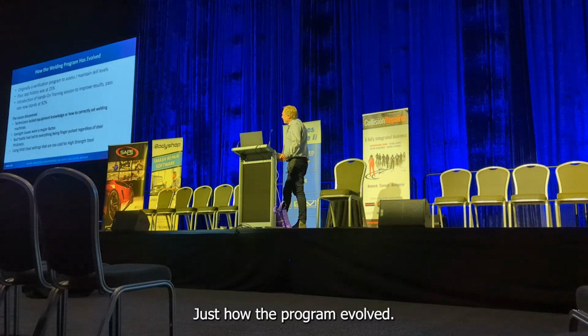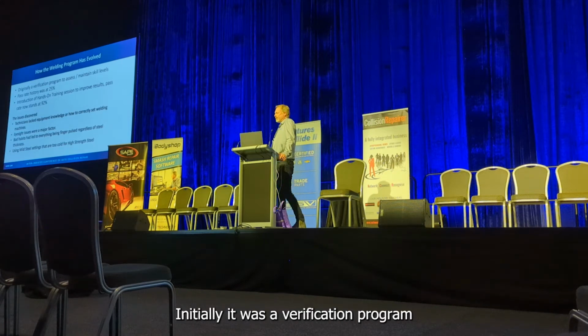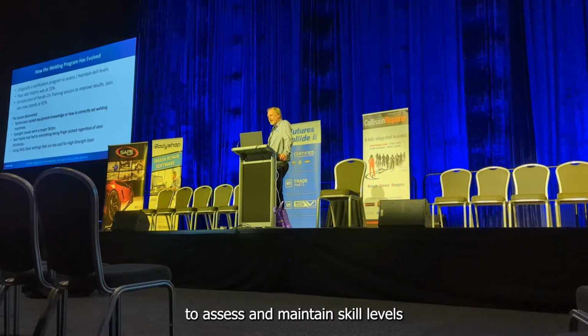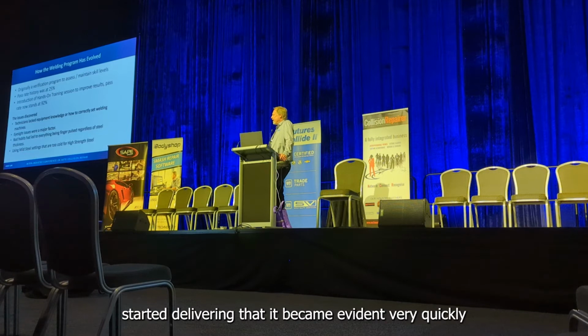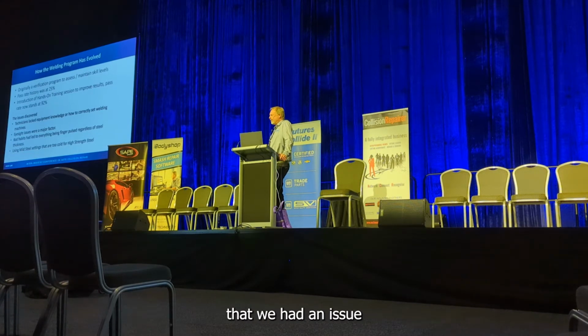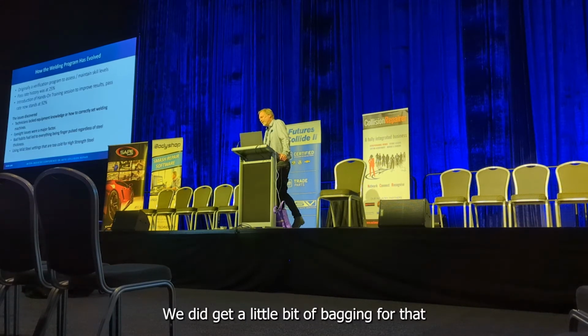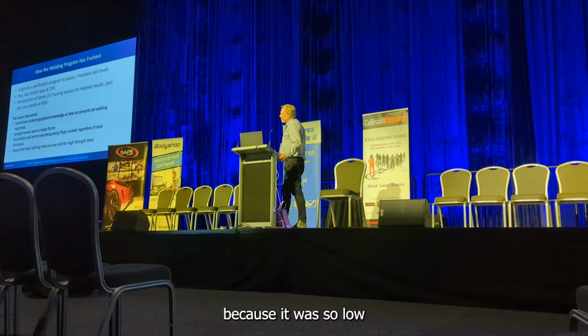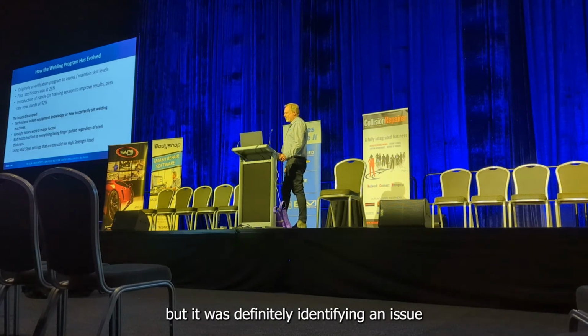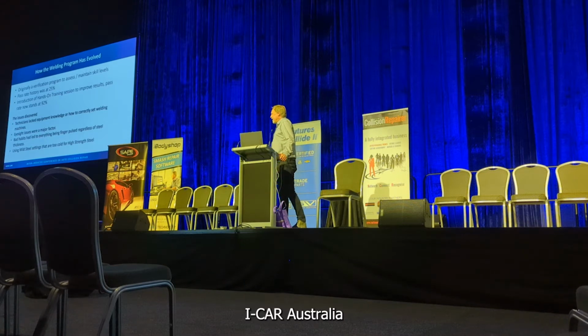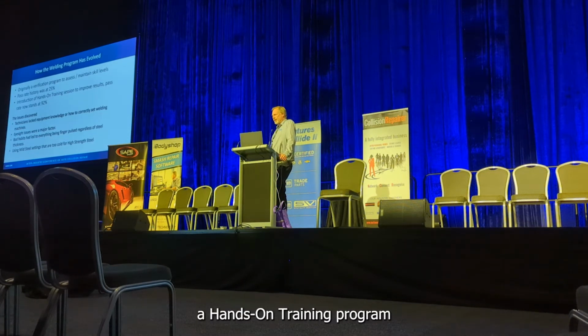Just how the program evolved. Initially it was a verification program to assess and maintain skill levels within the post-trade arena of the industry. When we started delivering that, it became evident very quickly that we had an issue with welding skills in our industry. The pass rate was at 25%. We did get a little bit of bagging for that because it was so low, but it was definitely identifying an issue we had.